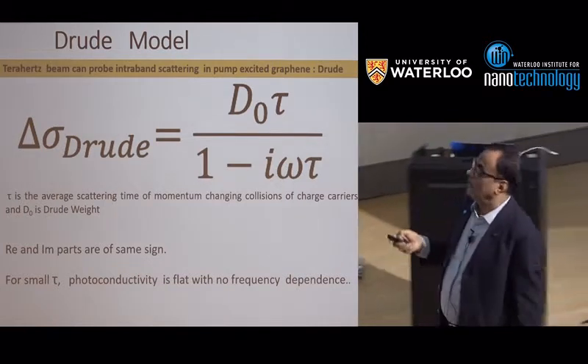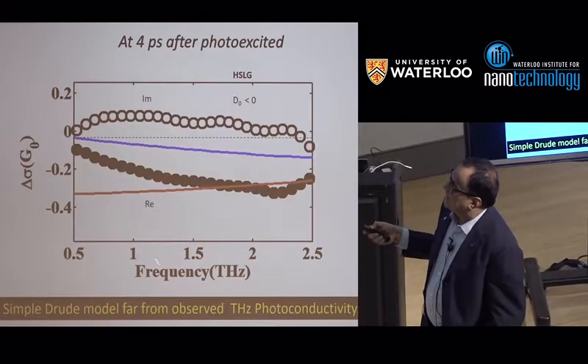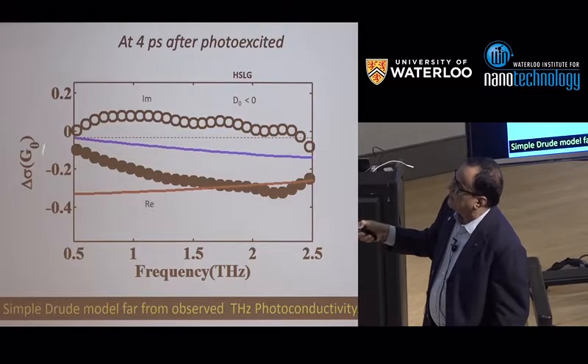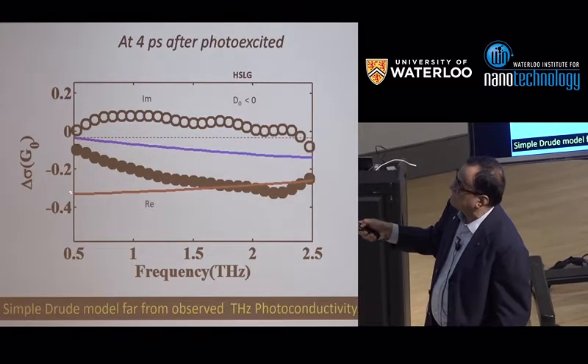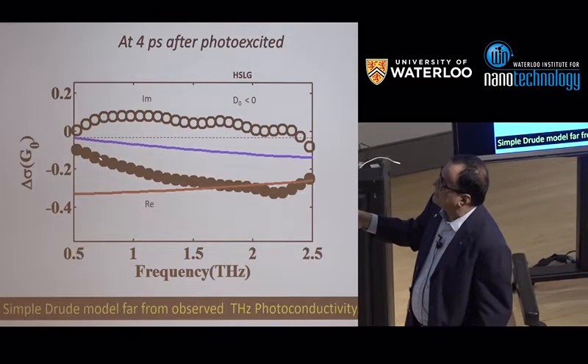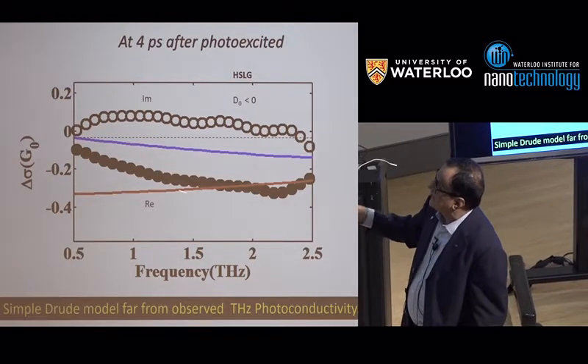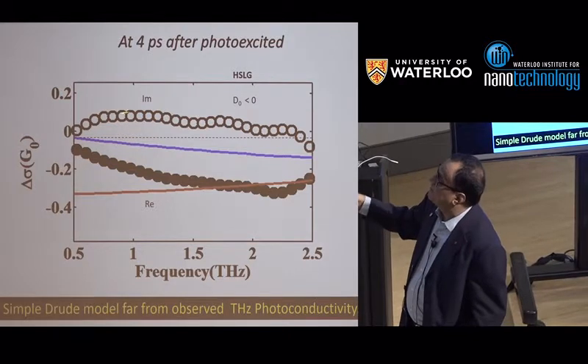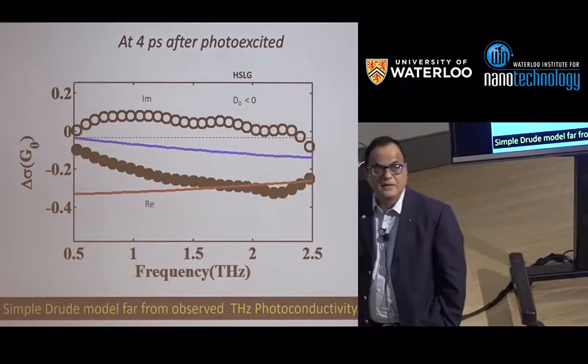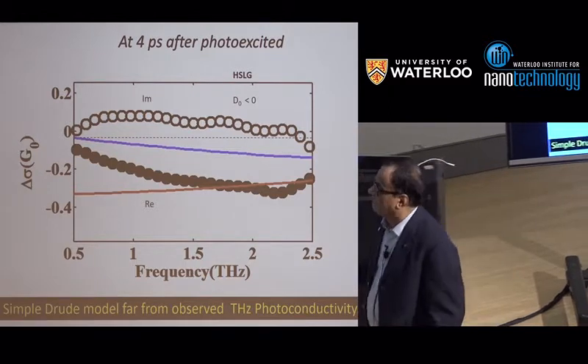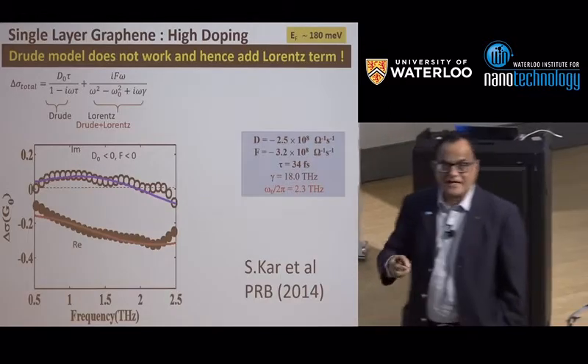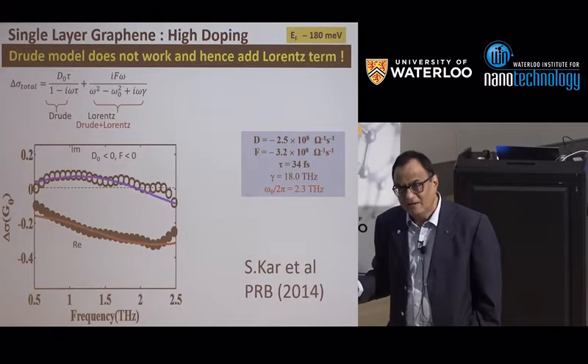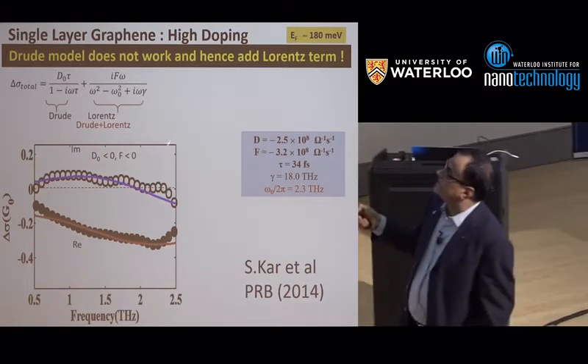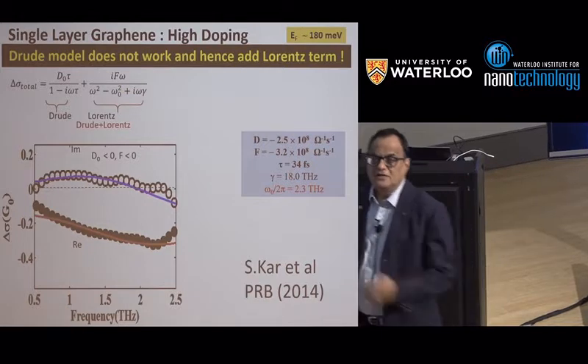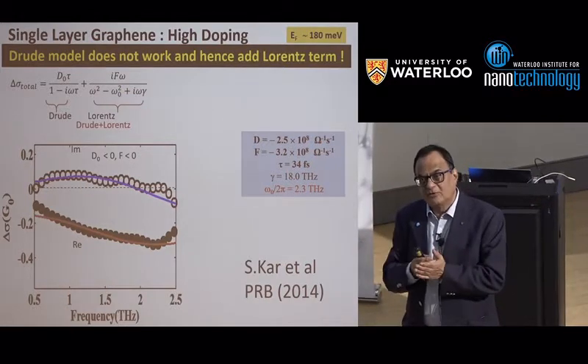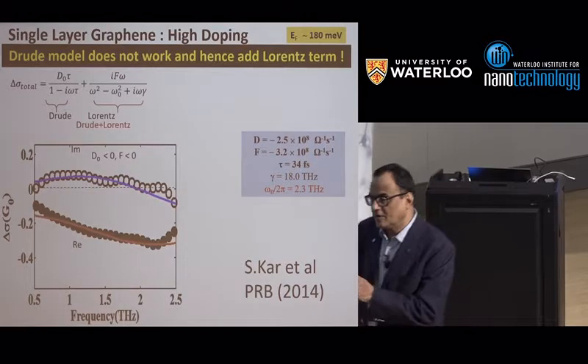But what we saw, and this was the first experiment, when we measured this, the conductivity of the single layer graphene was very interesting. The real part was negative and the imaginary part was positive. And this was completely different from Drude, what you expected. So as usual, there is a crisis in the lab because you don't know how to explain. So you do what physicists do best, you put a Lorentzian, and Lorentzian will explain everything in life, because if Drude doesn't work, put Lorentzian.